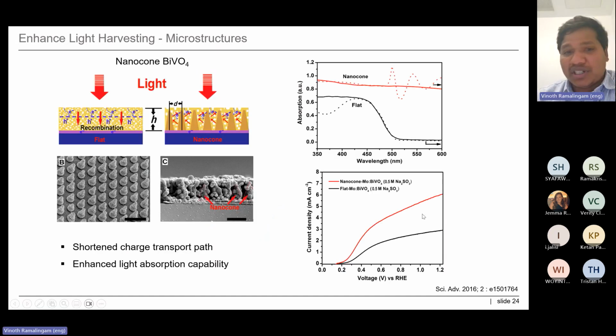Here is an example from the literature. You see they fabricated nanocone bismuth vanadate as a photoanode material, and compared to the flat one, the nanocone material has better absorption, as you can see here. In the case of flat, the absorption started decreasing after 500 nanometers, whereas in the case of nanocone, it shows excellent absorption all over the visible region.